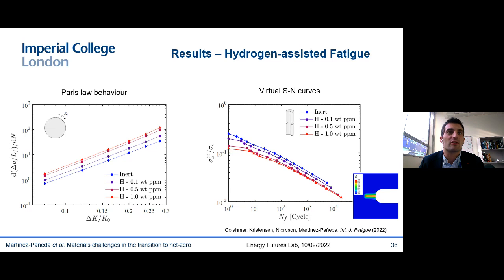And we can also predict the influence of hydrogen on Paris law coefficients or deliver virtual SN curves for any geometry or loading history. And I emphasize that the Paris law behavior and the SN curve are an output of the calculation. That means a prediction and not an input.